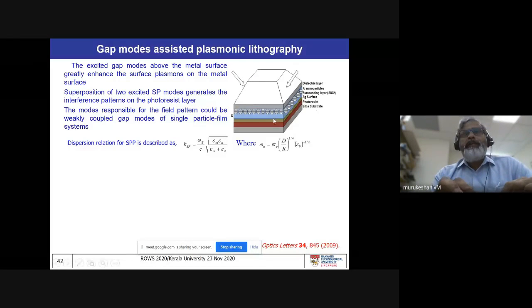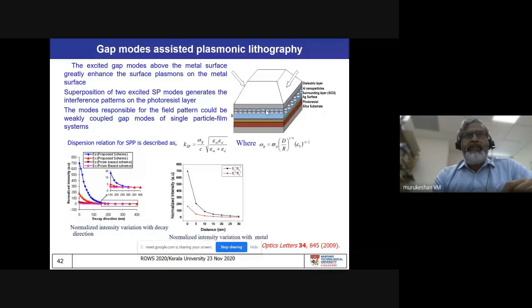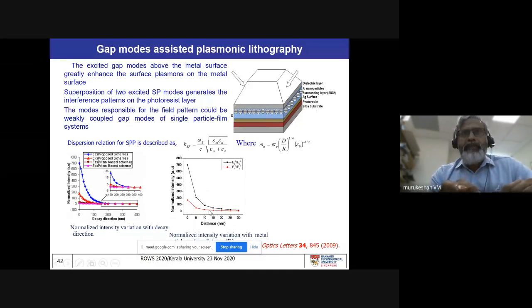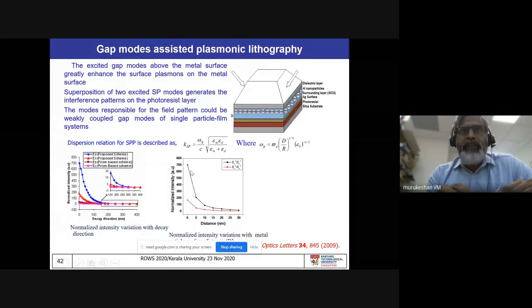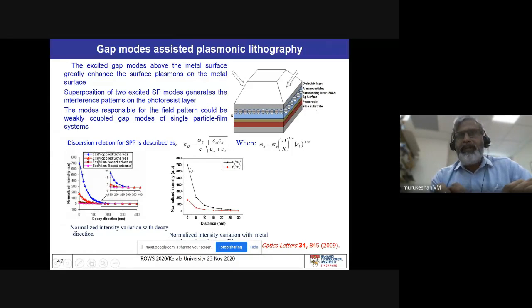And if you can take those modes and configure this in the same prism-based configuration, and you can actually pass counter-propagating waves on this layered structure, what you are going to observe is a very interesting thing. You can see that in this structure, the normalized intensity along the z-axis, that is Ez square, is much larger to the very near distance. You can see that much larger.